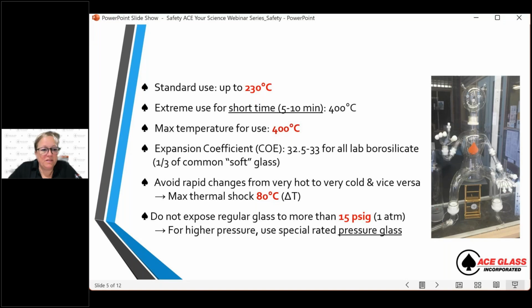Also, one very important thing is the pressure that we expose our glassware to. Standard lab glass should not be exposed to more than 15 psig, so 1 atmosphere. You shouldn't charge up your glass with nitrogen or argon, because that will cause it to explode.